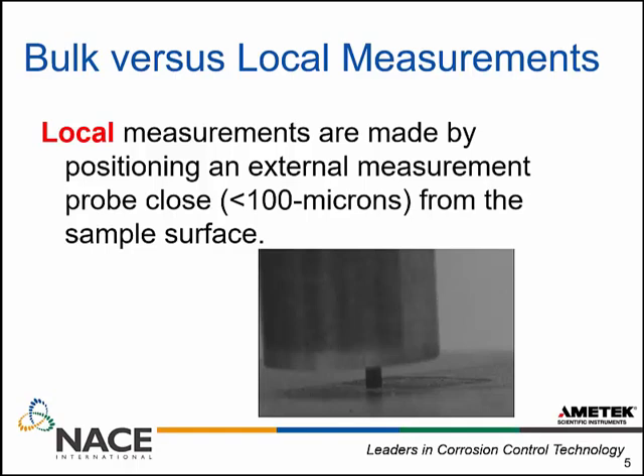In contrast, localized measurements are all about where the measurement is being made. Instead of measuring at the sample, I'm going to measure at a probe positioned very close to the sample surface — non-contact. When I say close, let's put numbers on it: less than 100 microns away from the sample surface. The closer I get, generally the higher the resolution. That's about the diameter of a human hair — I want to be about one human hair away from the surface without making contact. Then I'm going to scan over that sample surface and generate a data map.